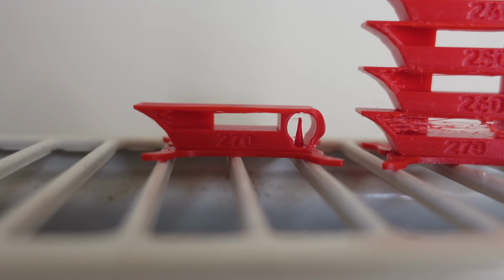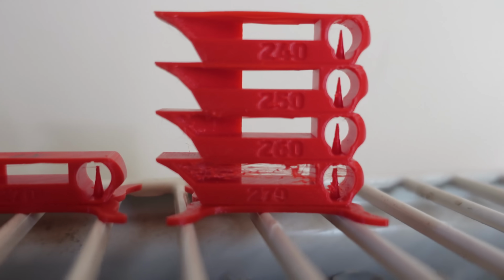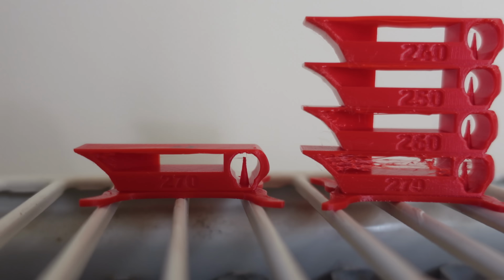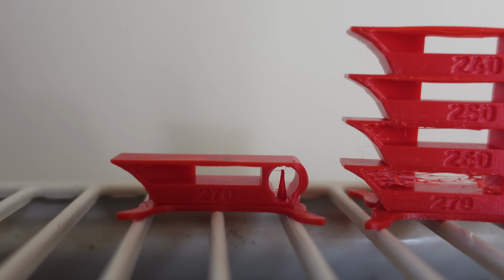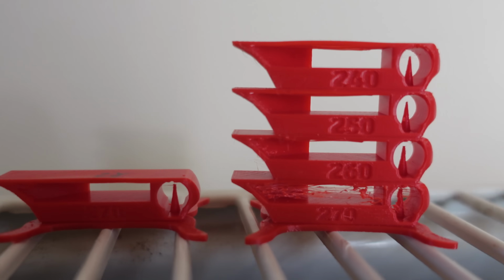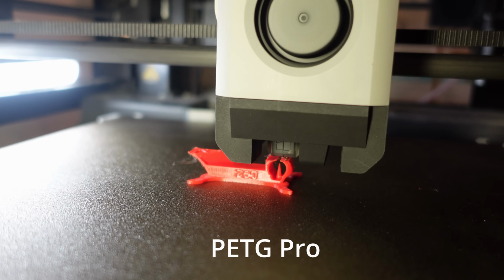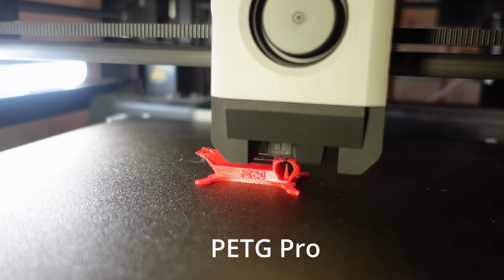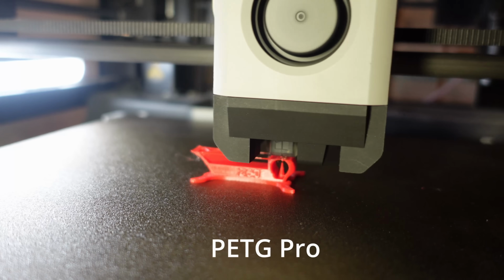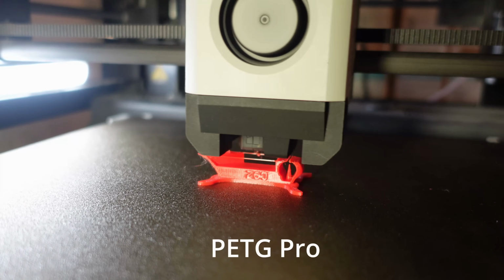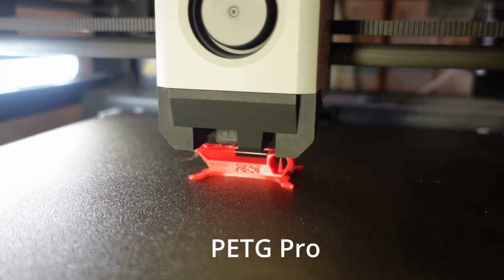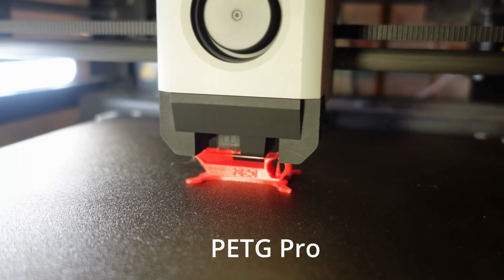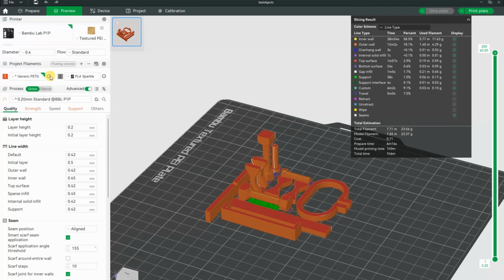I hope it's visible on the screen too, so perfect printing now on 270 degrees Celsius. So with the PETG the drying is important, especially with this high speed or rapid PETG. Looks much cleaner. This is the filament at 260 degrees Celsius because this will be the print temperature too. It started with the bridging. And now I know my print settings.